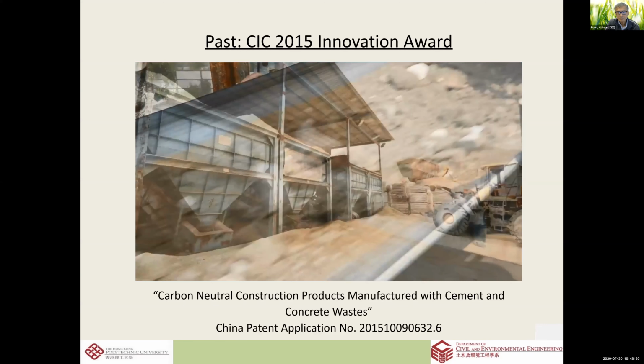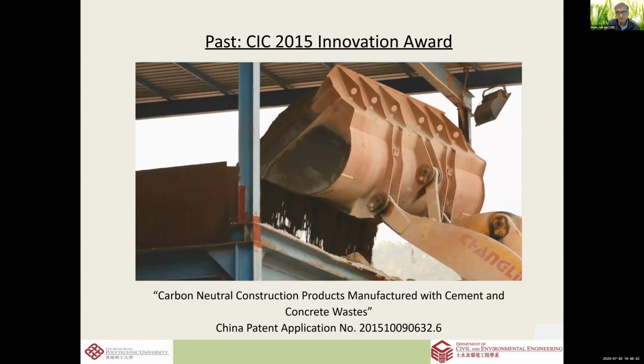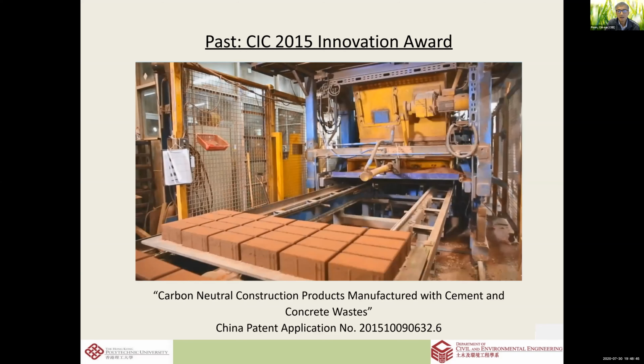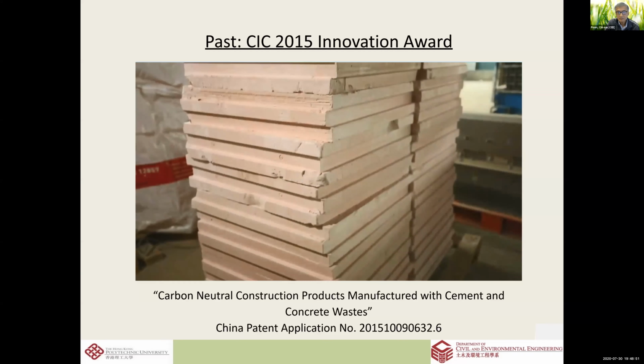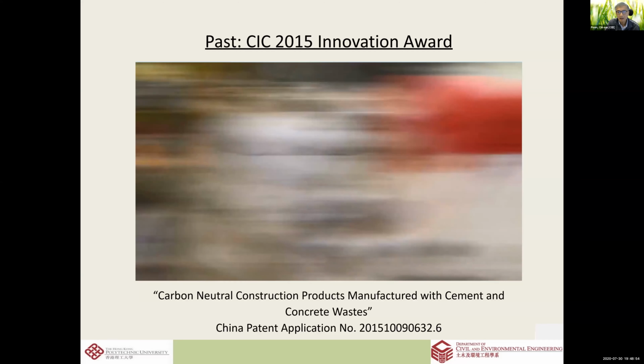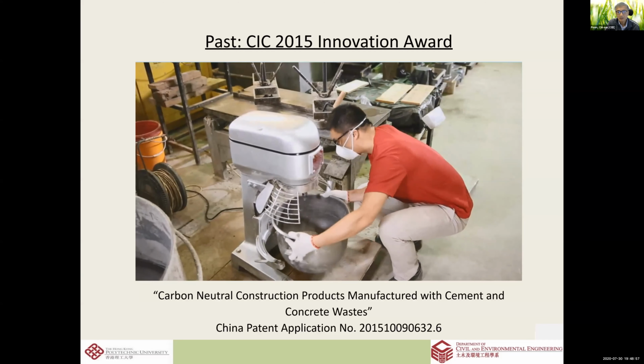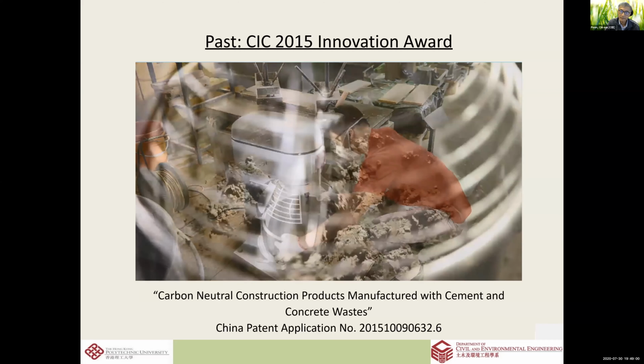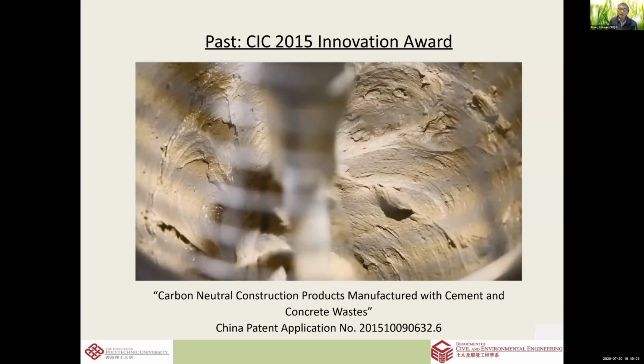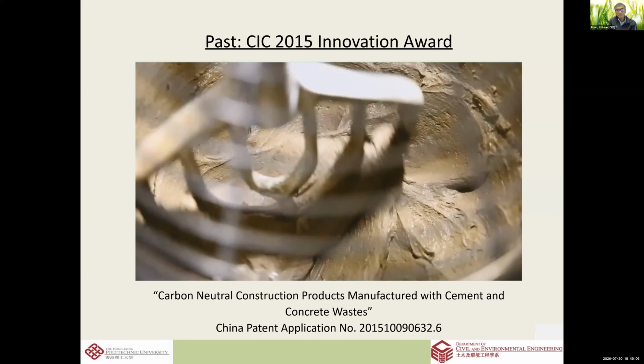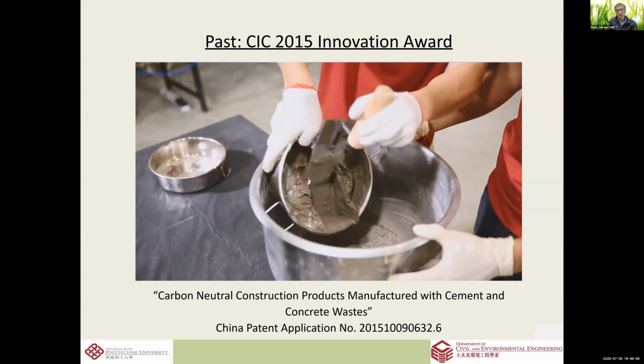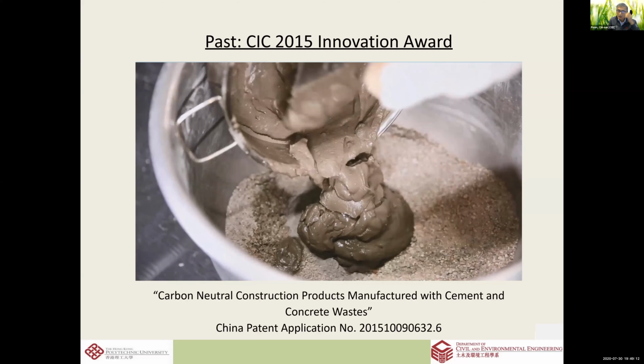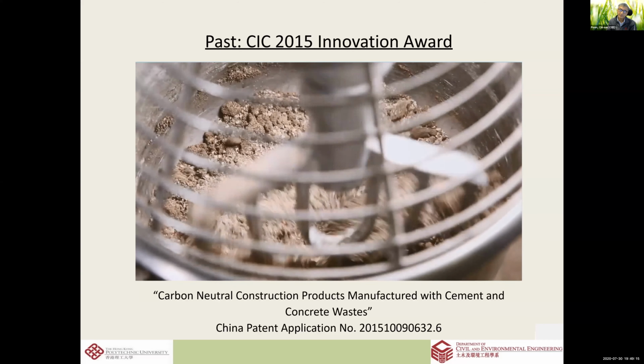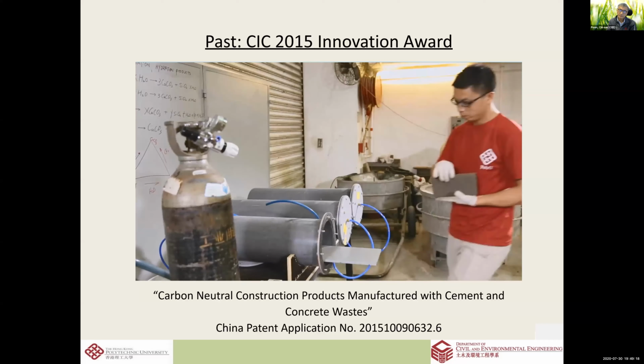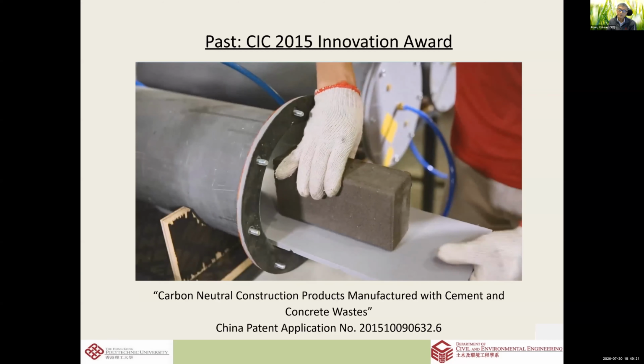More than 5 years' efforts devoted by the team has eventually brought to the birth of carbon-neutral concrete products. For instance, dry partition wall blocks, which not only are made from waste, but also cured by waste CO2. In the PolyU lab, the fresh cement slurry waste from concrete plants is firstly processed to a calcium and silicate-rich slurry paste. Then, the paste is mixed with fine aggregates produced by recycled fresh or old concrete in proportions determined upon required concrete performance. The mixture can be further fabricated into better quality dry wall blocks at optimized CO2 concentrations for a few hours identified by the research team.